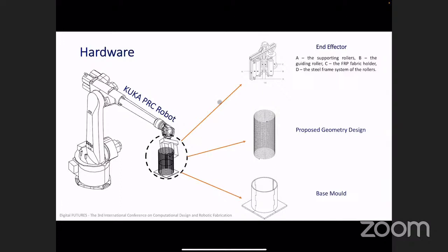The end effector is installed on the robot's 6-axis hand and tested. The fabrication process follows a spiral path, and hence the data configuration file was set for the robot's 6th axis, which rotates more than 360 degrees. From experience, it is suggested that the generated path planning script is verified by allowing the robot to run without any fabric and epoxy resin. After the successful completion of the dry run, the epoxy resin is used with the fabric.